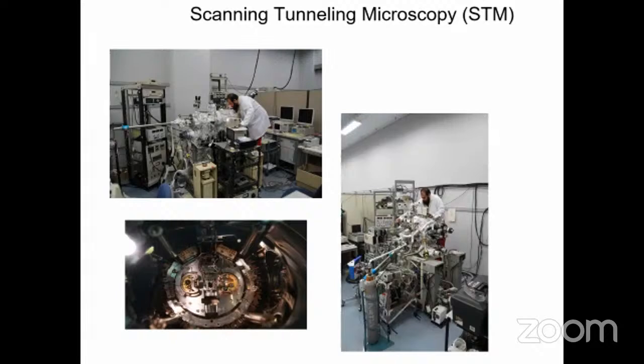In scanning tunneling microscope, we measure the tunneling current. These are electrons jumping from the tip itself to the sample by applying a bias voltage and trying to measure. The difference between STM and AFM is that AFM looks at the lateral resolution and can work in ambient conditions. But STM works in ultra high vacuum and the temperature can be varied as well. We are looking at the electron cloud, the electron density itself, not at the laterals like AFM. This is why we get higher resolution by using STM itself.